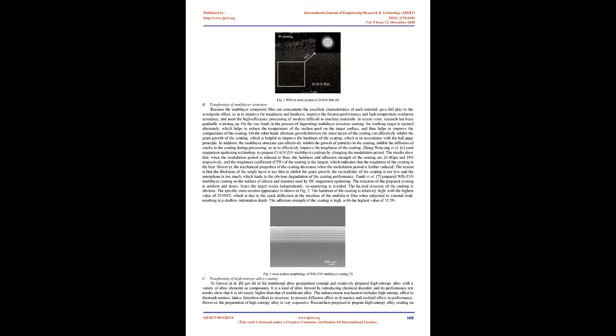On the one hand, in the process of depositing multilayer structure coating, the working target is opened alternately, which helps to reduce the temperature of the molten pool on the target surface, and thus helps to improve the compactness of the coating. On the other hand, alternate growth between the inner layers of the coating can effectively inhibit the grain growth of the coating, which is helpful to improve the hardness of the coating, in accordance with the Hall-Petch principle. In addition, the multilayer structure can effectively inhibit the growth of particles in the coating and the diffusion of cracks in the coating during processing, so as to effectively improve the toughness of the coating.